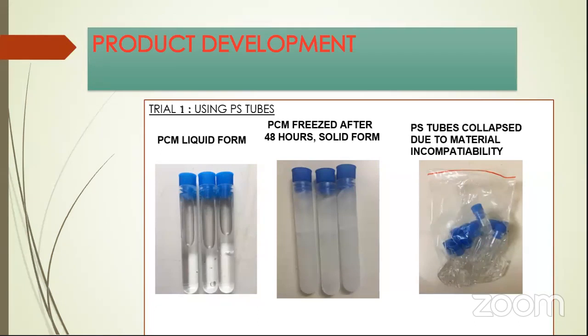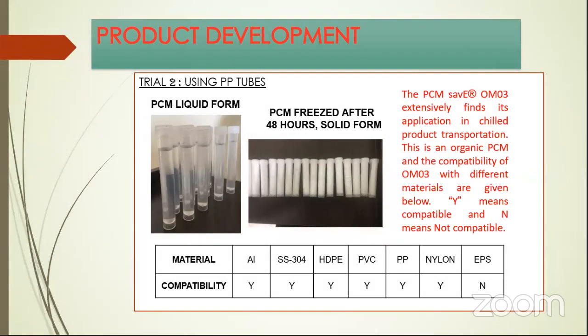Right, so initially we have taken polystyrene tubes, and this PCM is frozen after 48 hours and made solid form, whereas immediately that will be broken due to the material incompatibility. So we have not used this, and we selected polypropylene. This is sterilized at 120 degrees Celsius, and this is compatible with almost all the materials. So here the compatibility possibilities are given. So almost it's compatible with all the materials.